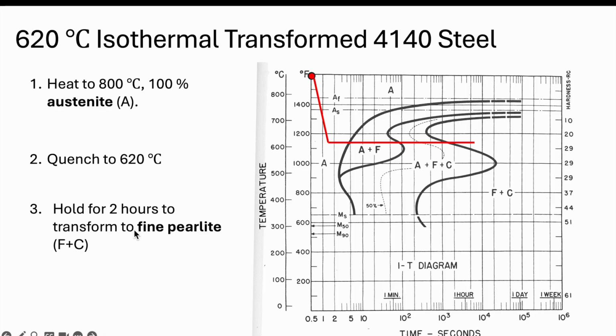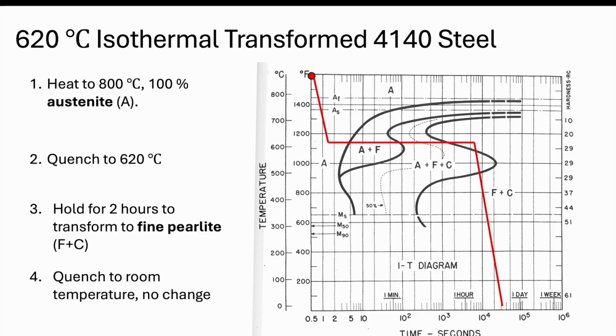And you might notice I have the word fine here. So on the lower end of temperatures, when we get pearlite, it's still pearlite, it's still layers of ferrite and cementite, but we put the fine designation there because the layers are closer together. They're smaller layers closer together. And so we call this fine pearlite. So the layers can change with the temperature. So we're going to see that, and we're going to see why we do multiple temperatures in this range. So this would be fine pearlite plus ferrite. And again, we quench to room temperature with no change.